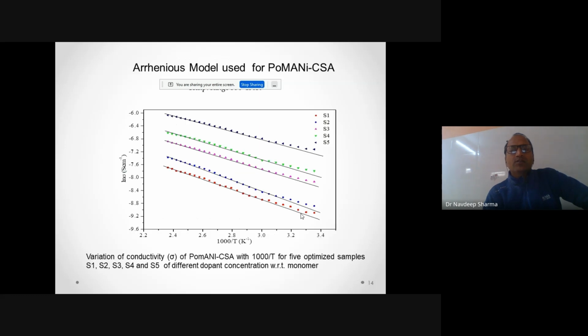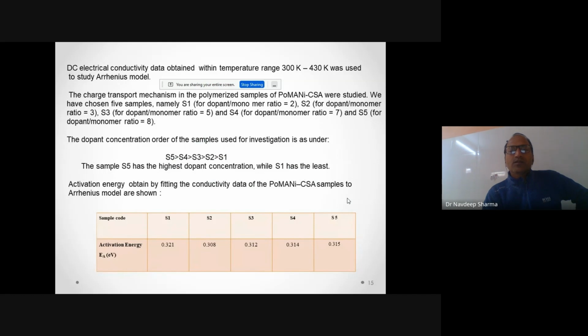And here the Arrhenius model is used for this poly(ortho-methyl aniline) CSA, and you have seen that for the samples S1, S2, S3, S4, S5, the conductivity range is 300 to 430 Kelvin, and after 430 Kelvin we have seen that the line is not fitting well. It means that this model is applicable between the range of 300 to 430 Kelvin, and the data obtained from this is the activation energy, which is very important to understand whether the charge is moving properly or not.